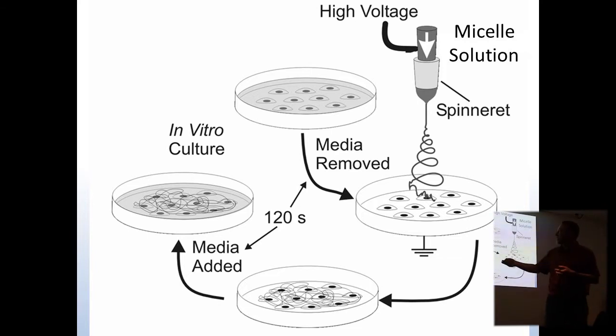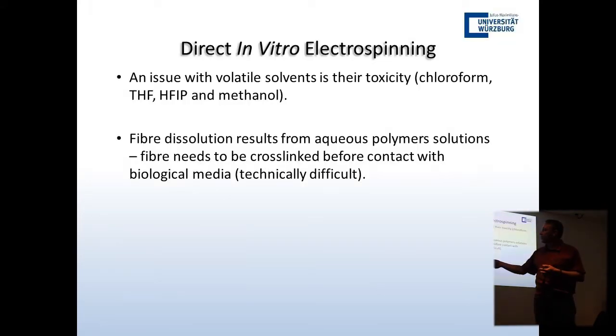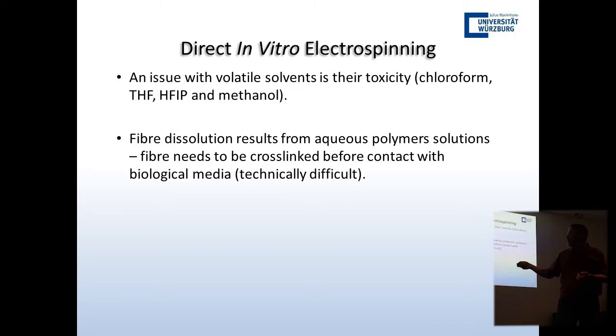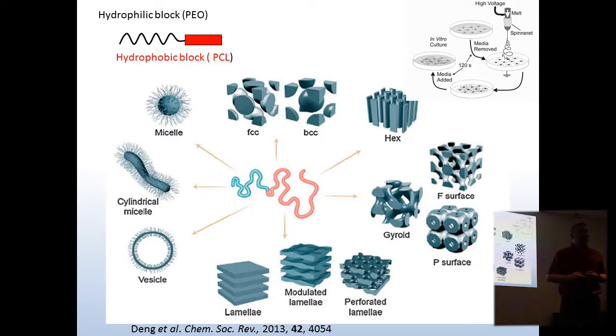This is technically really challenging, because a lot of the solvents that are normally used that aren't water are volatile and usually have some toxicity associated with them. If it's aqueous polymer solutions and it's not cross-linked by the time it hits the cells, it'll just dissolve again. It was incredibly tough, actually. It didn't work. I was persisting for months and months trying to get this transition to work.